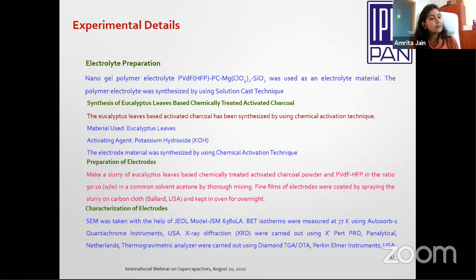We are not using, even till now, I am not using any lithium-based salt because it is really not easy to work with lithium. It is not safe to work with lithium. I know the performance is very good, but it is definitely not easy to go with. So that's why we are mainly working on magnesium salts, and comparing magnesium and lithium, we are getting almost comparable results. So we are developing our cells using magnesium salts and SiO2, silicon oxide, as a nanofiller.